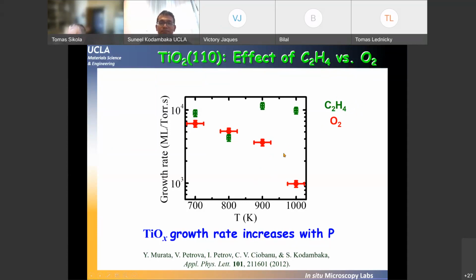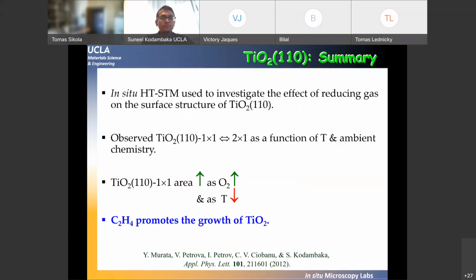And what we see, which is counterintuitive, is that exposing it to ethylene plus oxygen significantly boosts the growth of the stripe phase. Okay? And we proposed some theory to explain why this happens. I'd be happy to talk to you about what we think is happening. Okay, so that's about surface reactions. And again, it's now fairly standard to use scanning tunneling microscopy to study catalysis, and some of your colleagues are doing these types of experiments either here or they have done this in the past.